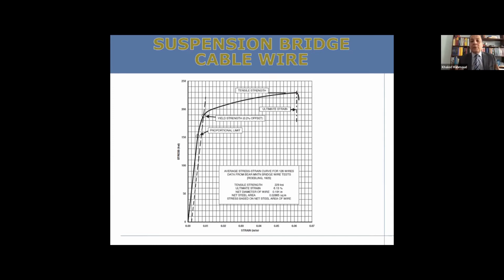Well, basically what we do is we have a rod material that's almost 1300 megapascal in strength, and about 14 to 15% elongation capacity, or the ultimate elongation. And you start successive cold drawing through dies up until you draw the final 5 millimeter diameter. That gets you that awesome strength, this is an old stress strain curve, of about